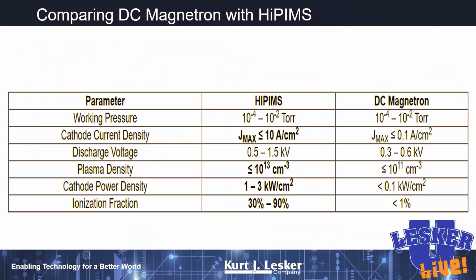So if we just do a comparison quickly between DC magnetron sputtering and HiPIMS, we have the same working pressure here, but notice that the cathode current density now is 2 orders of magnitude higher than what we saw with DC magnetron. But keep in mind that the time-ordered average is going to be about the same. The discharge voltages are a little bit higher. The plasma density is 2 orders of magnitude higher than in DC magnetron sputtering. The cathode power magnitudes are just much higher.